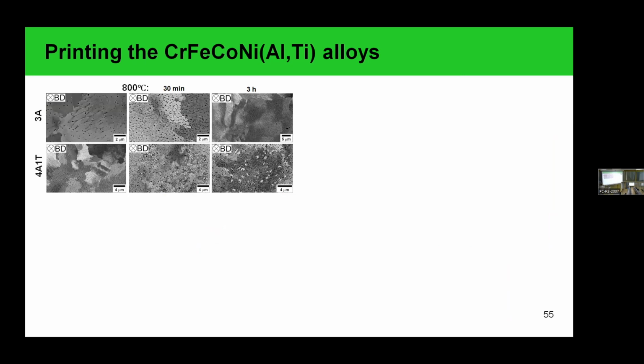Analyzing the structure, we wanted to achieve the idea that we can form an additional phase on the cell boundaries, and it can be reached with the annealing at 800 degrees Celsius for a short period of time, like 30 minutes. Longer annealing leads to the disappearance of our cell structure, and also new phase boundaries. In case of the as-built materials printed with titanium, even after a short heat treatment, we see plenty of phases formed during the as-built state and formed during the heat treatment.